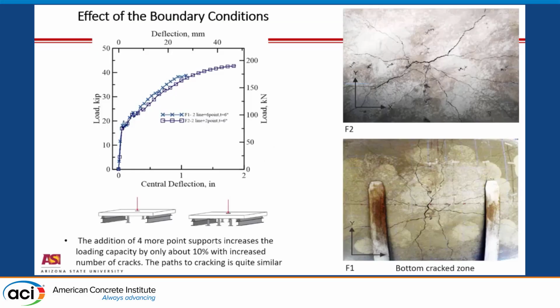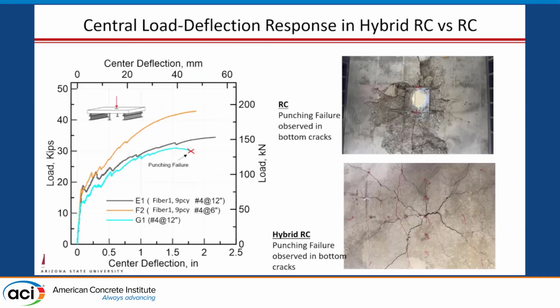But the more important thing is the nature of cracking that occurs when you go from one level of restraint to a higher level of restraint remains pretty much the same. We get the same pattern. So as long as you have about every 3 or 4 feet some type of a support or some type of a bolt to connect these, you basically get a significant amount of post-crack ductility. And this is the strain hardening that we get because that single small rebar that we have adds to the benefit.